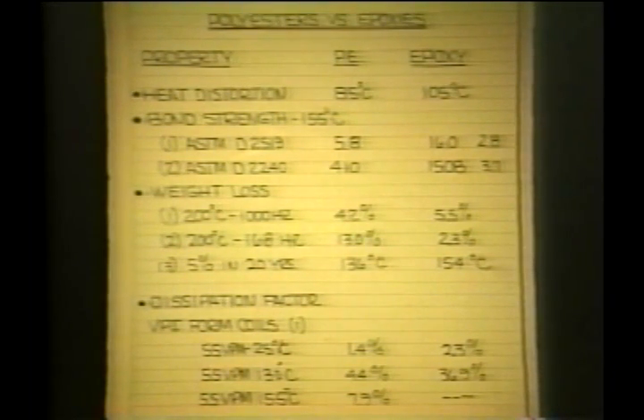And what I've done here also, I should mention, is pick a good epoxy and a good polyester so that we're not comparing the top of the line in one case versus the bottom of the line in the other. Bond strength is directly related to heat distortion temperature in most cases. And just for comparison, let's look at the bond strength of these two different types of resins as tested by two different standard ASTM tests. In one case, reported by source number 1, the polyester is 5.8 versus 16 for the epoxy. In another ASTM test, it's 410 versus 1500. The ratio is still in a range of around 3 to 1 or so difference in bond strength.